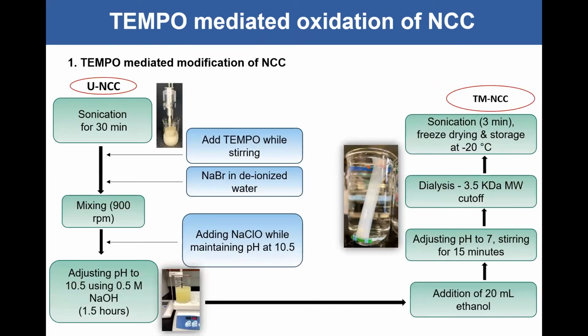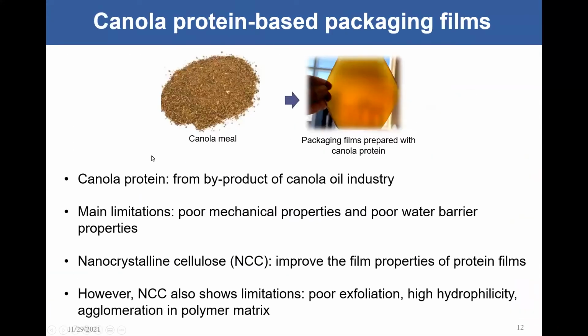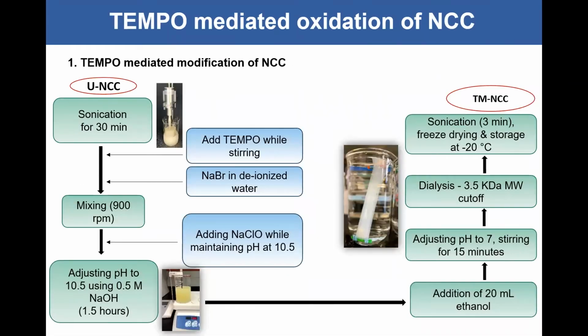Again, I'm not going to go into specific details about the method that we use for the oxidation of the nanocrystalline cellulose, but we basically use sonication to disperse the nanocellulose first, and then work with sodium bromide as a catalyst and sodium hypochlorite to maintain that catalytic reaction, and then we modify the nanocellulose to do the oxidation that we wanted. After the oxidation, we dialyze it, remove all the leftover chemicals, and then use that purified, modified nanocellulose for our experiments.